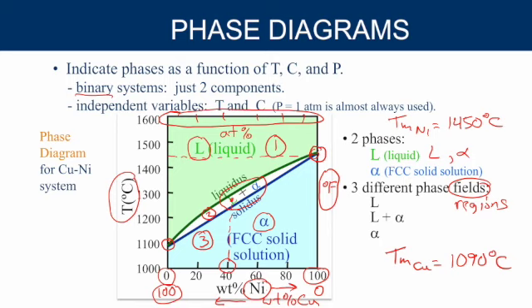And then the other way happens as well. If I have a solid phase, some of the copper that wants to melt will be forced to stay solid because it's interacting with the nickel. And this is the components, the amount of each copper and nickel that exist in each phase. So in the liquid phase, there's an amount of copper and an amount of nickel, and in the solid phase, there's an amount of copper and an amount of nickel, right? So we can calculate that.